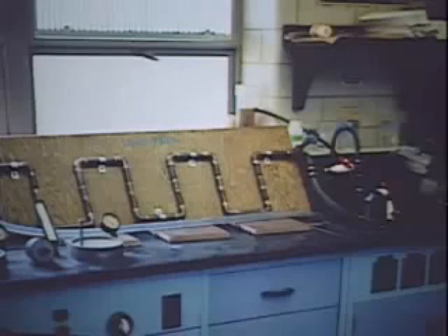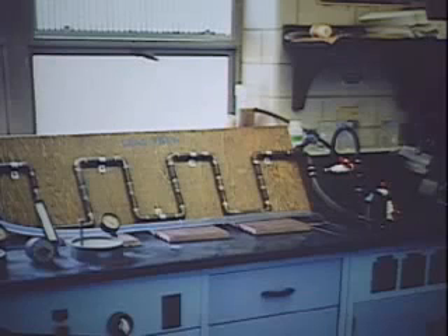Here we see the loop which the City of Atlanta built to test Seaquest for lead and copper reduction. The Seaquest at the low pH 6.3 without any pre-passivation was able to reduce lead and copper levels quickly and efficiently. Taking just two numbers for comparison, on 3/10/92, lead levels were 0.125 and copper levels were 0.784. Just 3 weeks later, on 4/3/92, lead levels were 0.002 and the copper numbers were at non-detect. This reduction is more than anyone could ask for in a corrosion control product.